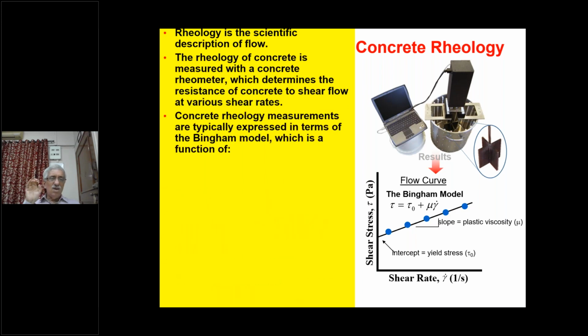Concrete rheology is studied in many places, using what is called a rheometer. Rheology is a scientific description of flow. We are now not interested in workability, slump and all. We are interested in the flowability of the mix in the pipe. The rheology of concrete is measured with a concrete rheometer, which determines the resistance of concrete to shear flow at various rates. Initially, the concrete has to break the friction between the pipe and the concrete being pushed through the pipe, and therefore the initial yield stress is important.